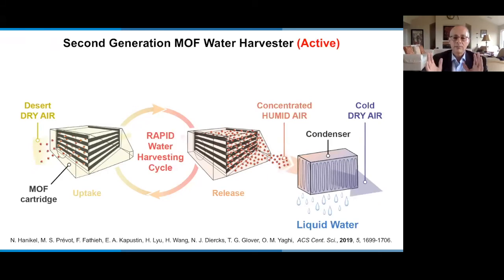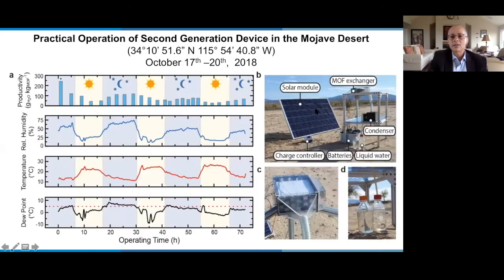So we designed another prototype for this MOF 303. This was a little bit more sophisticated. It had cartridges of MOFs where certain cartridges would take up the air while the other ones are releasing the water. We also interfaced the system with a solar panel so that we can do more than one cycle. And we took 1 kilogram of this MOF to the Mojave Desert, and I wanted to focus on the humidity level in the desert: during the night, relatively high; during the day, very low. And both during the night and during the day, you can harvest water.